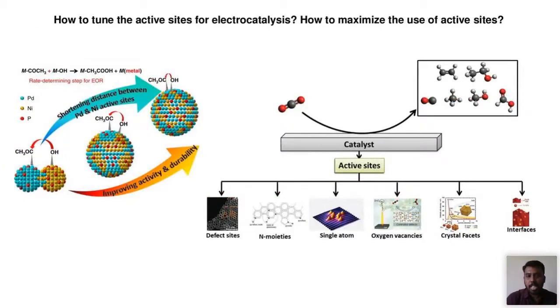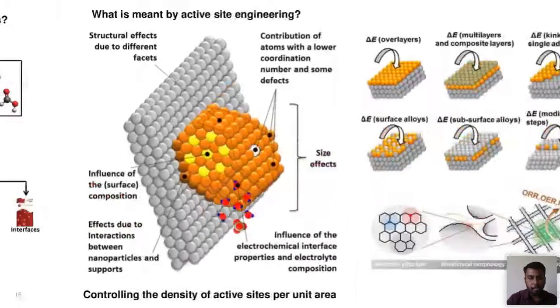How to tune the active sites for electrocatalysis, how to maximize the use of active sites? This can be done by shortening the distance between the metals present in your alloy. If you have palladium and nickel, then if you shorten the distance between these two metals, you can increase the number of active sites. Also, you can do active site engineering like introducing defective sites, nitrogen moieties, single atom catalysts, oxygen vacancies, and crystal facets and interfaces. A lot of things can be done by engineering the active sites, and you can improve the activity.